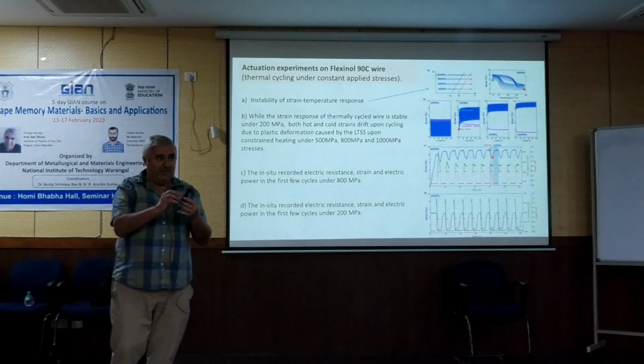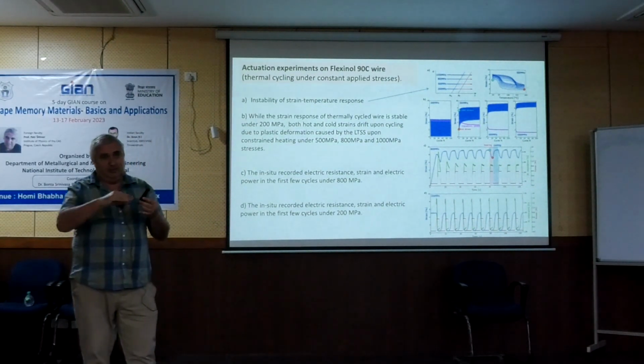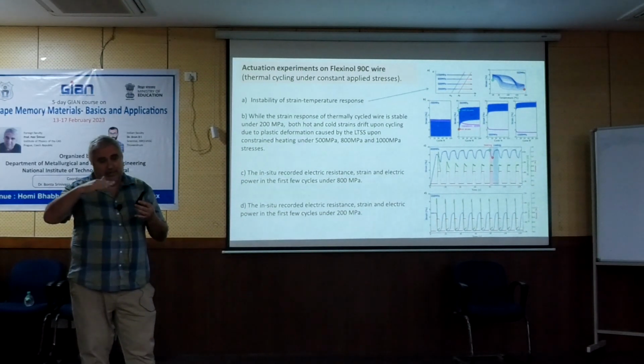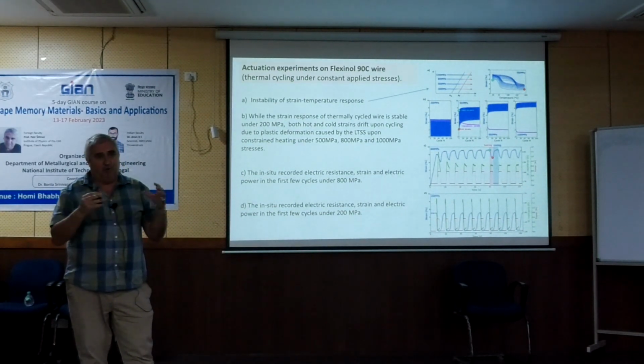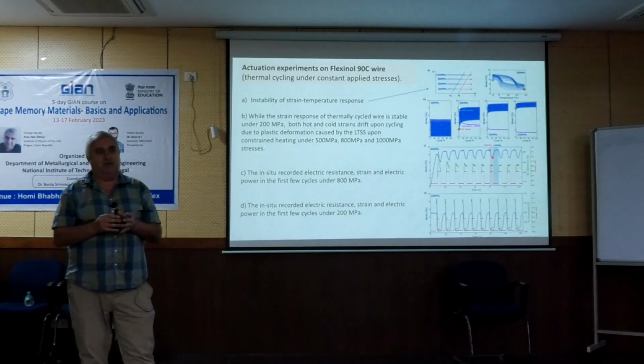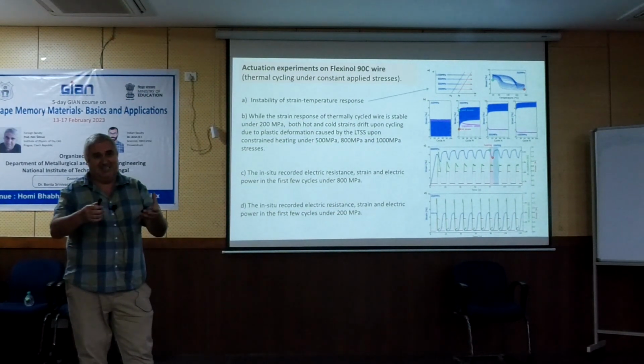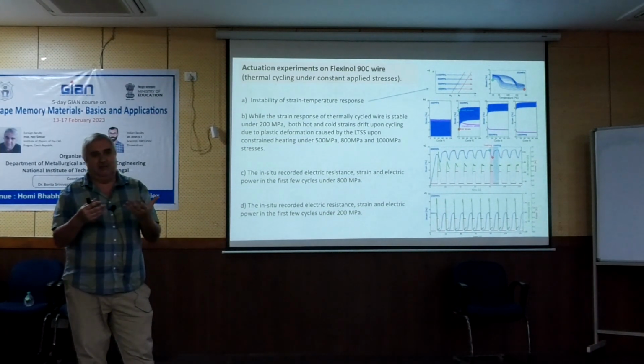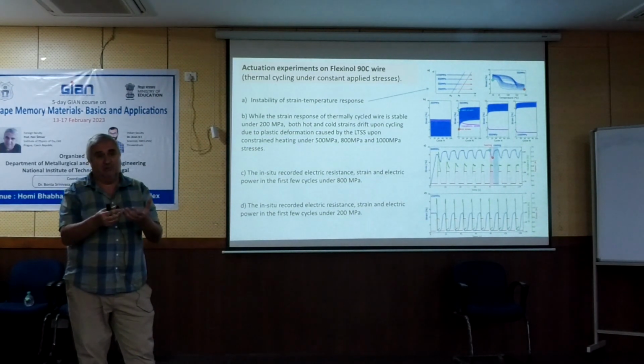So if one makes shape memory film, you can make micro pump, you can make any kind of vibration damper. So working in low dimensions with nitinol is very promising. So for that you need the devices which can deform thin films. So very load cell sensitive to 1 Newton or less. There are no commercial testing machine for thin film, so you have to build your own.